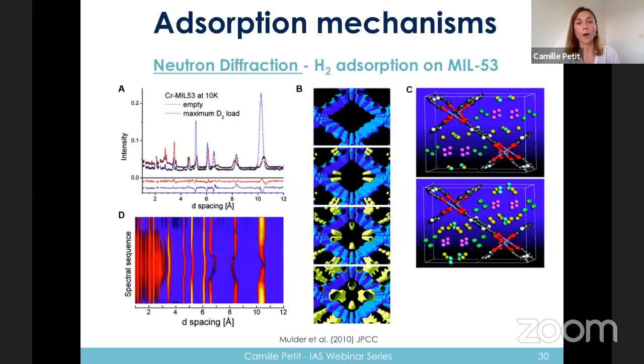Here I take the example of neutron diffraction. And the advantage of neutron diffraction is that it will be able to look at very light elements, unlike X-ray diffraction. So here that technique has been used a lot, for instance, to monitor hydrogen adsorption in MOFs. And I take here the example of MIL53. So if you look at the graph A, for instance, you have different patterns, whether the MOF is empty, so activated, or whether we have started the adsorption of hydrogen.